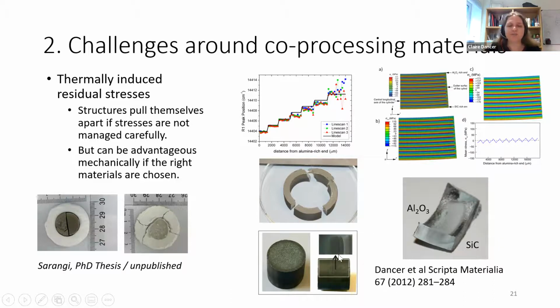Then we took a bit of a step back and had a look at what's going on with the residual stress, and found that you can mitigate some of these residual stresses by taking this sort of graded layering approach to the material. We can gradually change those properties in this direction. This is work I did before I even started on metamaterials, so it's sort of related but not the same. We can do these modeling pieces of work, actually measure the residual stresses, and find ways to keep those below the level at which the material will crack and pull itself apart.